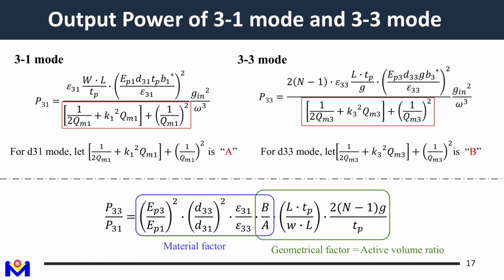So in material, we have EP3 and EP1. This is Young's modulus. And later on we will talk about it's not only Young's modulus. In general, we talk about the stiffness of the beam. So in general, EI, that's including the Young's modulus and moment of inertia, determines the stiffness of the beam. And here we have D33 and D31, the ratio of the piezoelectric constants. And like I just mentioned, D33 is in general higher than D31. And also we have epsilon 31 versus epsilon 33. This is the dielectric constant. If this is a homogeneous dielectric material, then we will say epsilon 31 is equal to epsilon 33, and then we can eliminate this parameter.